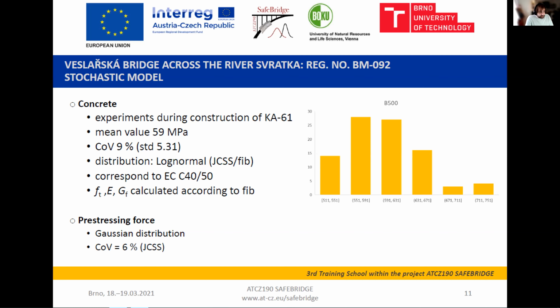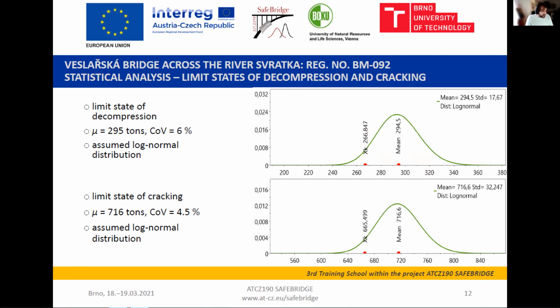And the second random variable was the pre-stressing force. According to the JCSS Probabilistic Model Code, we assume a normal distribution and a coefficient of variation of 6%. Note that this is the pre-stressing force after losses, and the mean value was obtained from the original documentation, from the original calculations. So once we performed these 30 simulations and obtained these load deflection diagrams and stress fields, etc., we analyzed these three quantities of interest. First of all, the limit state of decompression. As you can see on the figure on the right-hand side, there is a log normal distribution with a mean value of 295 tons with a coefficient of variation of 6%. We assume log normal distribution because it's typical and it's recommended by codes to assume log normal distribution of resistance.